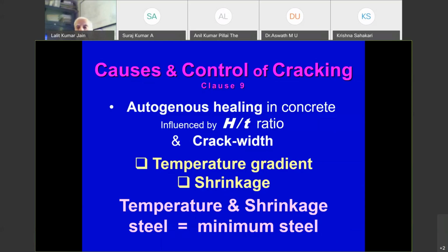If we pour concrete at 40-45 degrees, you find that within 24 hours a peak temperature will come, because the chemical reaction is proportional to the temperature of concrete, and in a small period a lot of chemical reaction takes place and the temperature gradient is very high. Temperature generated is very high. So inside the core of concrete, temperature is high. Outside at the outer face, the concrete will have temperature adjusting itself to the ambient temperature. It will be lower than inside, and we get a temperature gradient. At later life, this itself will contribute to temperature gradient and cracking. Similarly, shrinkage of concrete takes place, and shrinkage gradient also takes place.